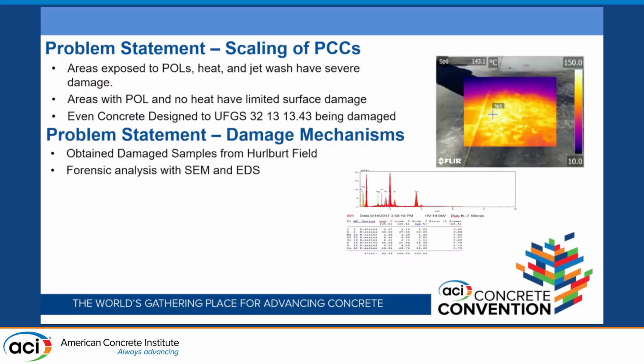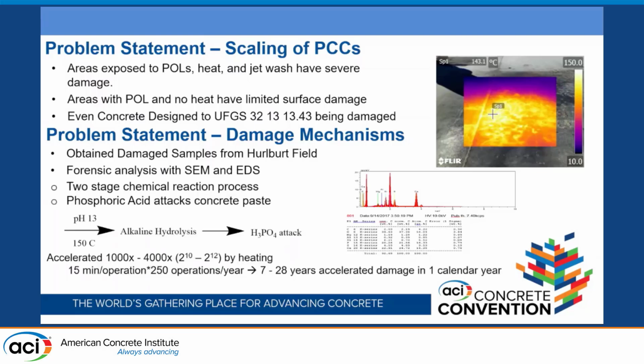So first step, we had to figure out what was going on. So we sent somebody out. He took thermal imaging while the aircraft was starting operations. We obtained damage samples, and then we did forensic analysis with SEM, EDS, and XRD, and a host of other forensic equipment that we have. Long story short, the high pH of concrete is reacting with the POLs and forming phosphoric acid, and that phosphoric acid is attacking the binder of the concrete. So you get this iterative damage process: scaling away the binder, then aggregates pop out, and then you're exposing more binder, and it's a layer-by-layer damage type thing. And the heat only exacerbates that process.